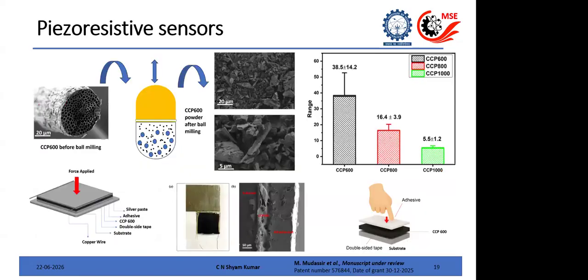Now you can actually make this not as a single fiber. You can powder it and make sensors out of it. So what you see here in the figure is a small sensor which is formed by this powder. You powder it with a ball mill. And this is a very simple design.